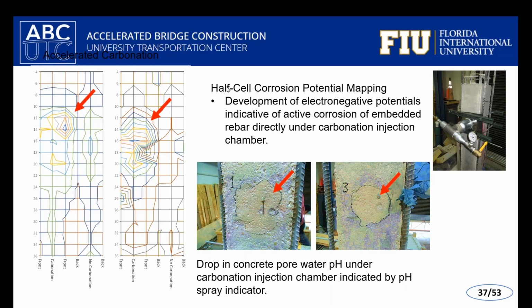We use those bars to measure the half-cell potentials embedded underneath, and that is what those contour plots are on the left-hand side of this slide. Essentially, where you see the circular contours is where we have more electronegative potentials. I apologize, I just realized I don't have the scale for you here, but those circular contours are where we have our more negative potentials, indicative of active corrosion. And around that contour, outside where that vessel was placed, we have the more electropositive potentials, indicating where the steel remained passive. So we were pleased that we were able, in a very short amount of time, to reproduce this amount of carbonation corrosion to the bars underneath.